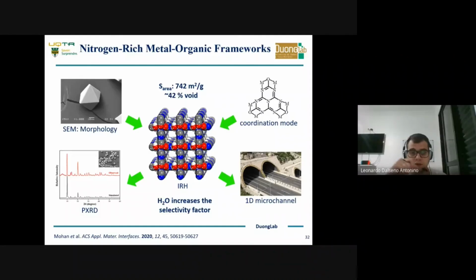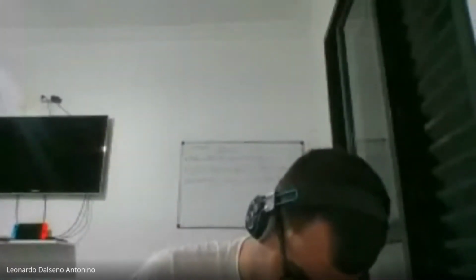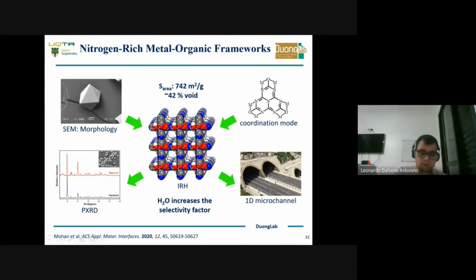The surface area of this type of material that we have created is not that high. It's only 742 square meters per gram. The void is around 42%. But what is interesting, and I will show it later, is that we have good selectivity for gas separations. And one thing that you maybe cannot see clearly here, sorry, because you are not used to seeing this structure, is that they contain coordinated water that will help us with the selectivity.